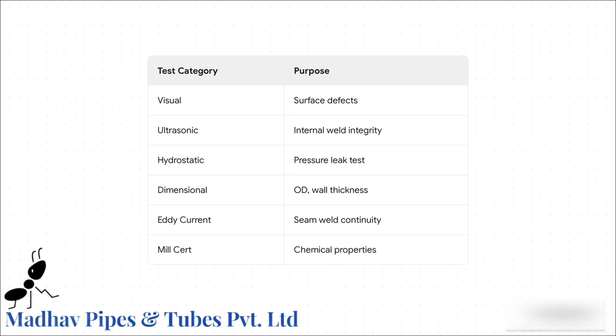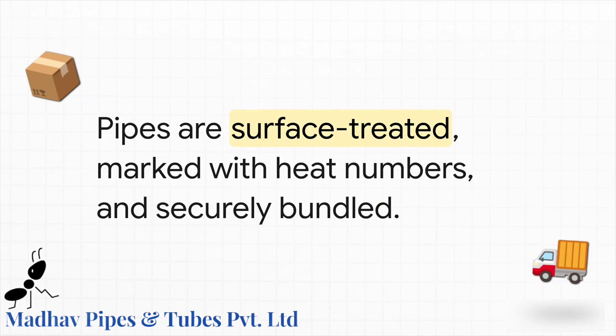They meticulously audit the dimensions, run eddy current tests to check for seam continuity, and finally, they generate a mill certificate. This permanently documents the exact chemical and mechanical properties of that specific batch. Only after passing that gauntlet do we reach the true final step. The approved pipes are cleaned and surface treated based on whatever the customer needs. This could be a heavy-duty internal and external coating, galvanizing, or maybe just a simple varnish. Then they get uniquely stenciled with their heat numbers and dimensions, and finally, they are securely bundled with steel straps,